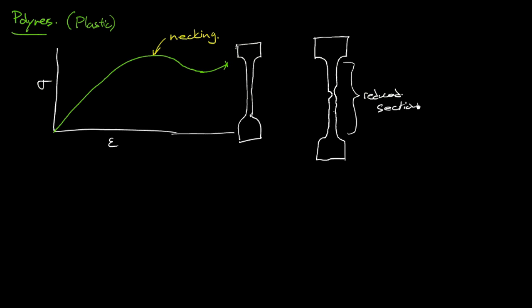And the interesting thing about polymers, or one of the many interesting things—of course they're super exciting—is that that neck, see in a metal, that neck is where it's going to break each and every time. It's the beginning of fracture. But for a polymer, stretch that out a bit, it can continue to load bear even after it's necked. So what you see is you actually see this elongation of the neck.